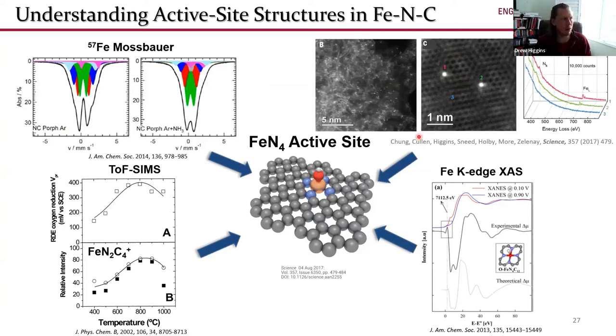But the key problem with that, and I think many electron microscopists will tell you, is that any type of contamination, like iron ions from your beaker or silicon floating around, could contaminate your sample and give you these bright spots. So the key thing that needed to be done here was some sort of spectroscopic characterization to point and say, yes, this is an iron atom, and yes, there is nitrogen in the vicinity, all within this graphitic framework. And this was really the first ever study that conclusively painted that picture from a spectromicroscopic standpoint.